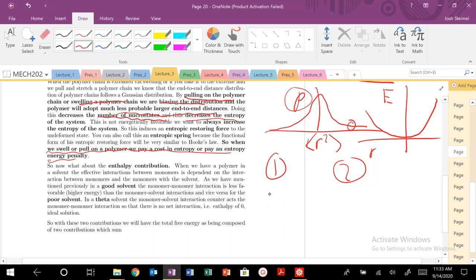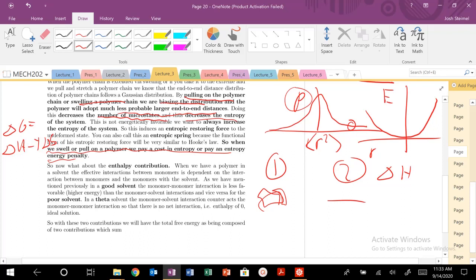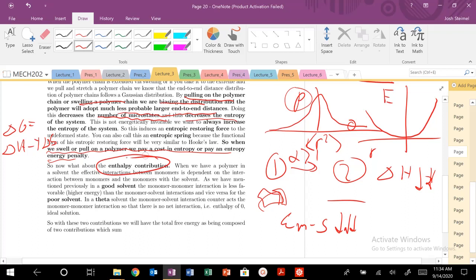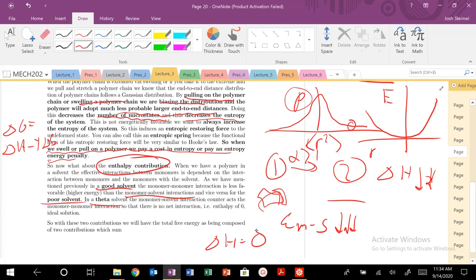What about the enthalpic contribution in the transition from state one to state two? We have to consider both H and S. Well, there's actually a driving force enthalpically to go to the extended state. If we put our polymer into a good solvent — alpha greater than one — we have favorable energetic monomer-solvent interactions that are low in energy. Thus, delta H decreases and energy decreases. That's the enthalpic contribution. When we're in a good solvent, we want to maximize those interactions and lower our energy. In a theta solvent, delta H is zero — the monomer and solvent are effectively the same, so there are no favorable or unfavorable energetic contributions; it just wants to maximize entropy.